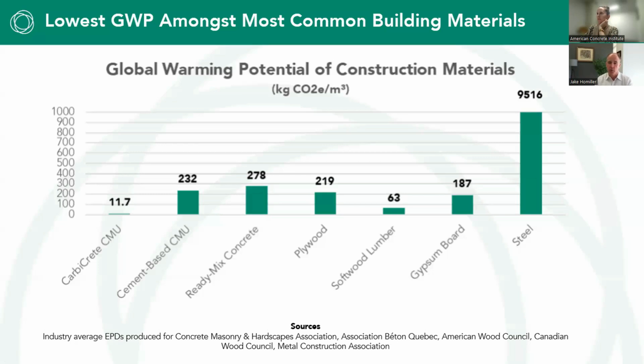One of the things that's really important when people are looking at projects, as far as project developers or project owners, is looking across the different building materials that can be used for different projects. And again, we're at 11.7 for a CarbiCrete CMU. You can see cement-based CMU about 232, ready-mix concrete of 278. Even when you compare to softwood lumber, which is often touted as being a greener, low carbon footprint material, we're substantially below softwood lumber from a GWP standpoint. And then obviously you compare to steel as a construction material, it's dramatically higher in its CO2 impact in its production.